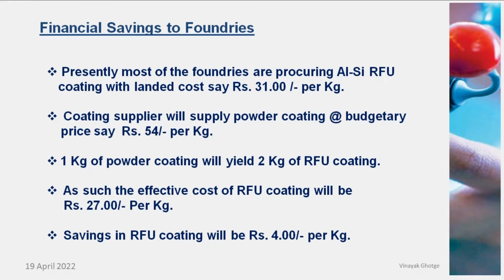1 kg of powder coating will yield 2 kg of ready for use coating. So the effective price of RFU coating will be about 27 rupees per kg. Hence, the saving in RFU coating itself is about 4 rupees per kg. Now in this, you can add certain things like electricity used by foundries, but the electricity used is very, very nominal. The cost of electricity cannot go beyond 5 to 10 paise per kg. It is hardly about 3 to 4 units per day, so it's very nominal.